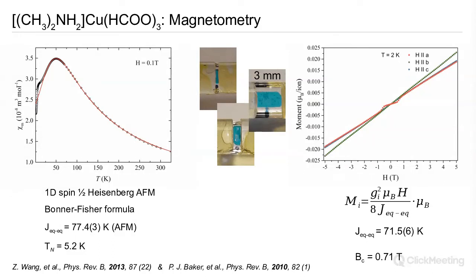We can derive a simple model where J appears in the denominator. We can fit the gradient and extract again an exchange interaction of about 72 Kelvin, so in good agreement with the susceptibility data. We also see this little wiggle occur at about 0.7 Tesla. This is indicative of the antiferromagnetic moments lying along the A-axis, and this would then be a so-called spin-flop transition, where the critical field BC is some measure of the anisotropy energy that's keeping the magnetic moments in that direction.